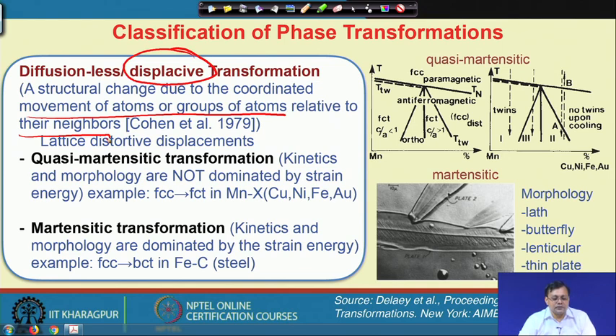This diffusionless transformation or displacive transformation could be of many different types, and we will try to focus on these two types of transformation. One is Martensitic transformation, another one is Quasi-Martensitic transformation. You may not have heard this Quasi-Martensitic earlier. However, this Quasi-Martensitic is a type of lattice distortive displacement. This particularly means that there is a distortion in the lattice. Distortion in the lattice somehow means that in this particular case the kinetics and the morphology of the product phase is not dominated by the strain energy.